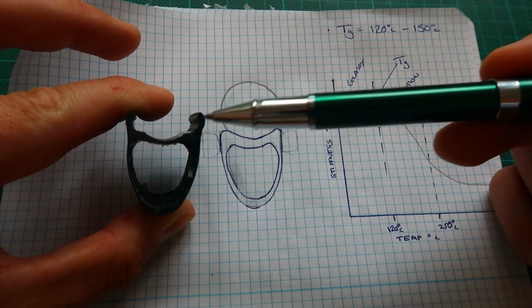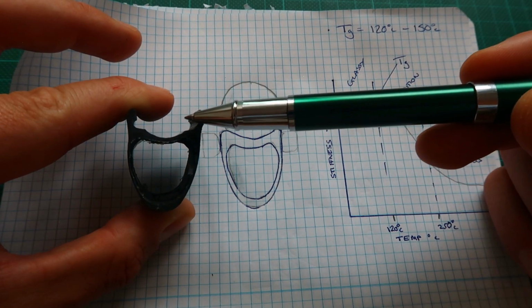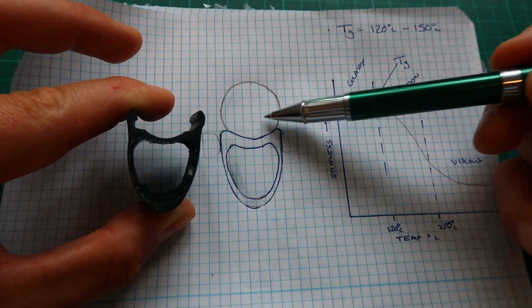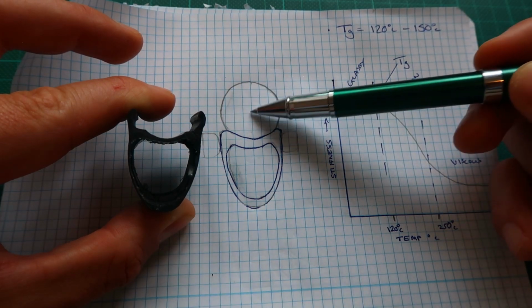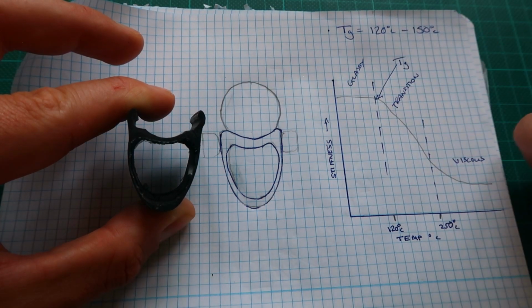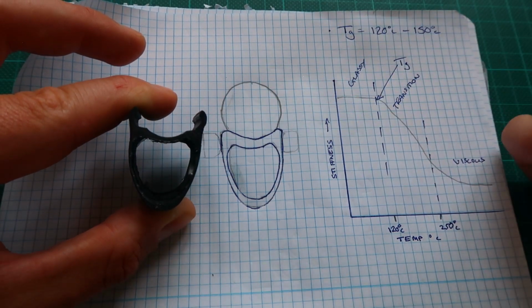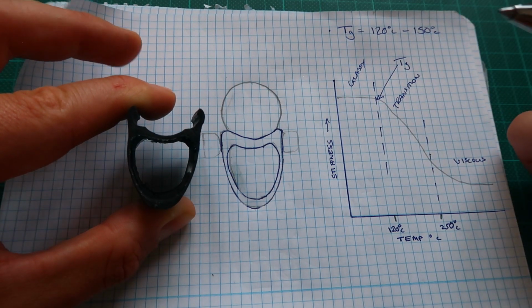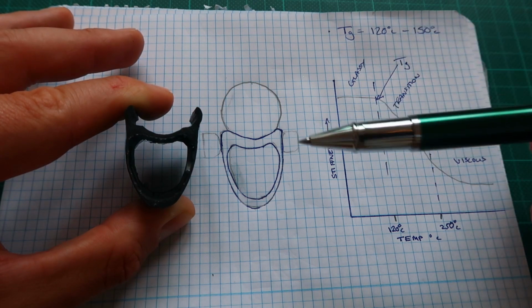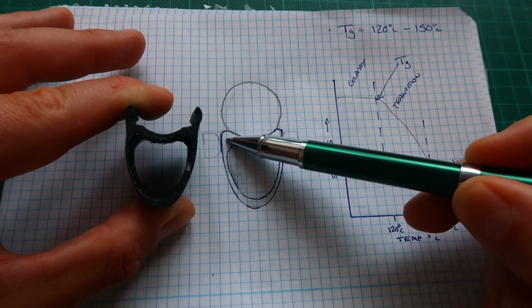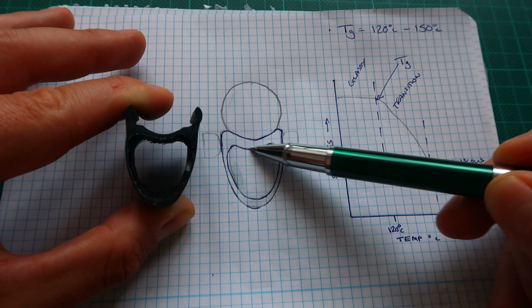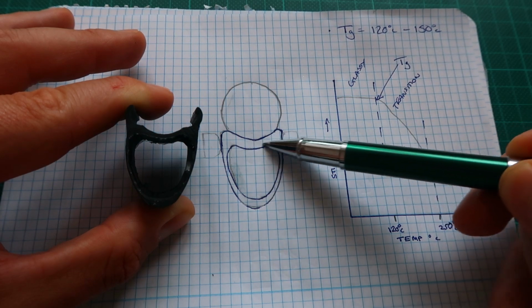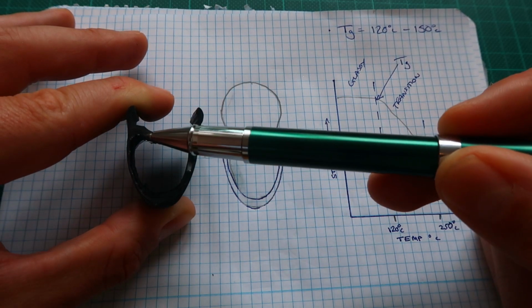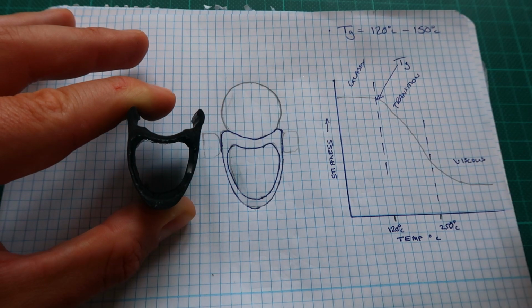So you've got this open, unsupported area at the top, which can be blown out by the tyre pressure. If you've got 110 psi inside here, it will just push out on the sidewall, and if this gets soft, it'll bend out like this has. Now, the tubular is inherently a better structure because the top of the brake track is tied together by this member here, which on the clincher, this part, is completely unsupported.